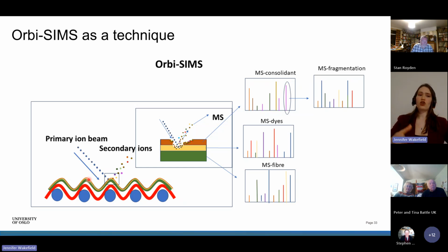This OrbiSIMS is an Orbitrap mass spectrometer, which is a slightly different, newer type that gives very, very high resolution. And it can give you more precision. I'm going to come back to that later. But what you do is you send this primary ion beam down, you get these secondary ions that come up, and that goes to the mass spectrometer, and you identify the mass of every ion that comes up. So it gives you a fingerprint of everything that's in that material that you're analyzing.